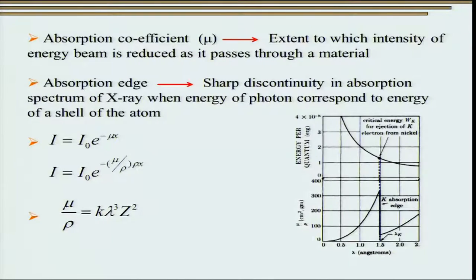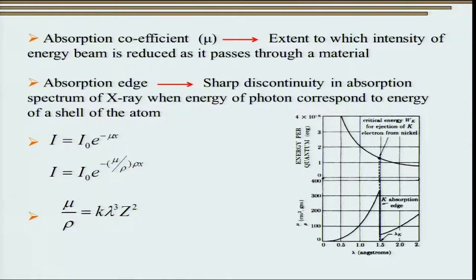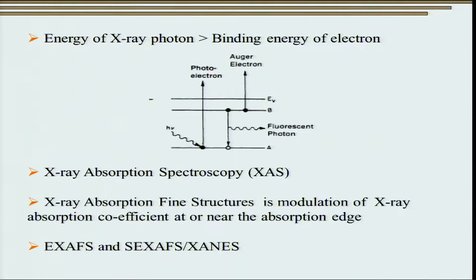The relationship between μ and ρ is not only wavelength dependent but also atomic number dependent. On the right-hand side, we can again see the curve where we have a critical energy Wk for ejection of K electrons from nickel, corresponding to a steep drop in intensity and absorption of the copper X-rays seen in the earlier case. When a photon of energy hν is incident and has sufficient energy, it can knock off an inner shell electron, provided the photon energy is greater than the binding energy of that electron.